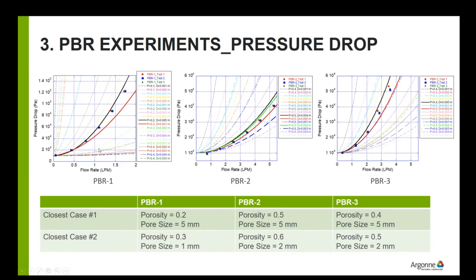And also we analytically calculate the pressure drop value and compare this calculation value to the measured data. By comparing these two values, we can estimate the porosity of the relocated fuel. So porosity of the relocated fuel was varied from 0.2 to 0.3 for PBR1. PBR2 has the highest porosity of 0.5 to 0.6, and PBR3 shows the middle range of porosity between PBR1 and